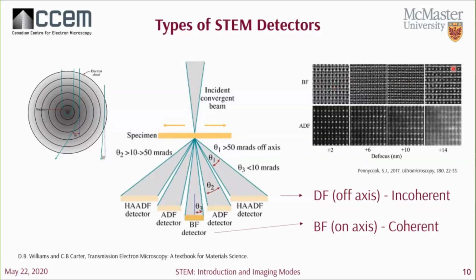When we increase the angle of our detection, collecting more higher scattered electrons, we transfer to our annular dark field detectors, which collect these off-axis electrons that have been scattered to higher angles relative to the optical axis. These detectors are donut shaped, so that the on-axis beam is not collected.